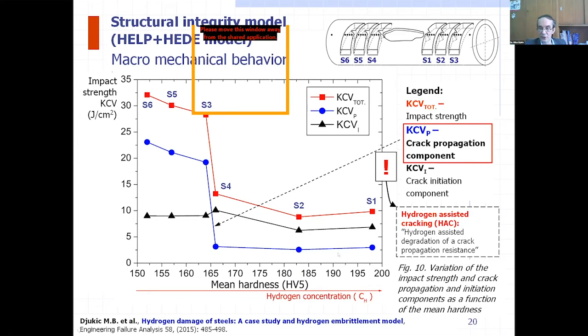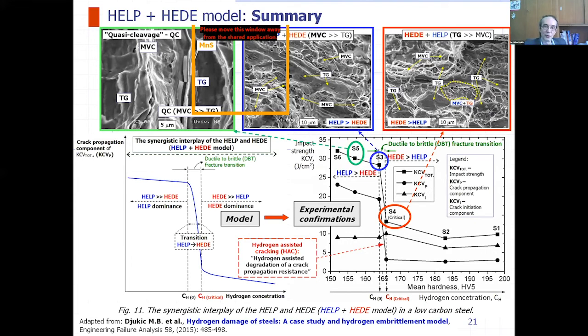With a further increase of hydrogen concentration, we have an additional drop in the crack propagation component of impact strength, but also a drop in total impact strength and a slight drop in crack initiation strength. So crack propagation components are related to hydrogen assisted cracking. We have here a very sharp drop of crack propagation resistance of the material due to effects of hydrogen.